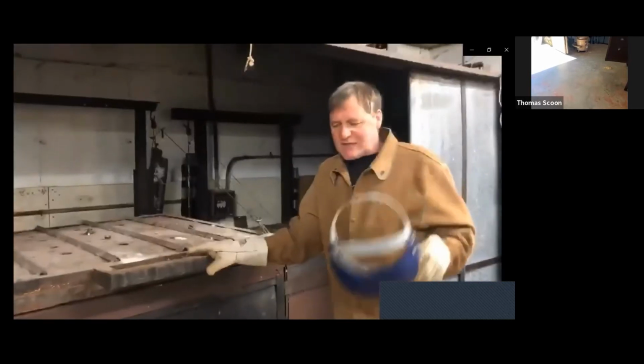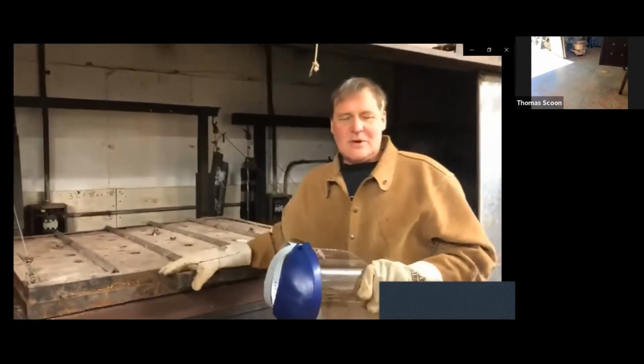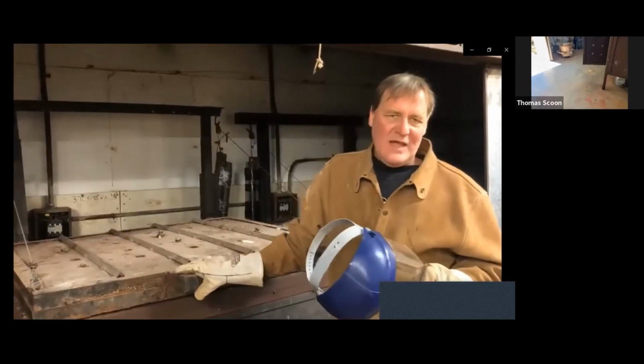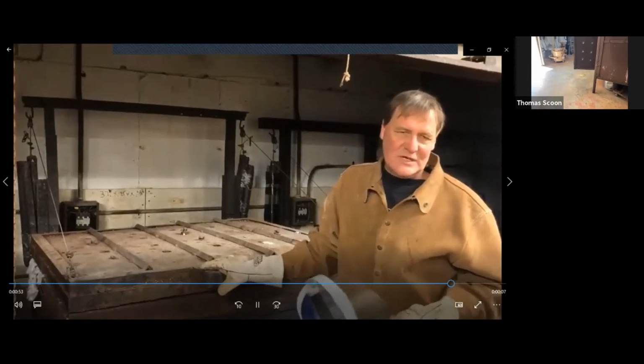This was a lost wax casting. The pieces are almost cast out. I'll turn the kiln off and have it go to 1,000 degrees. From there, it'll start annealing, slowly cooling from 1,000 to 0, which could take about 2 weeks. Basically, it's a big custom-made kiln, and it likes electricity.